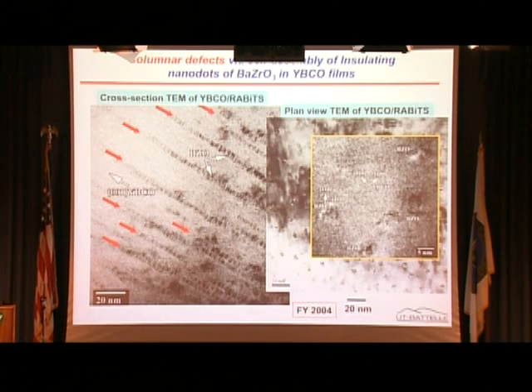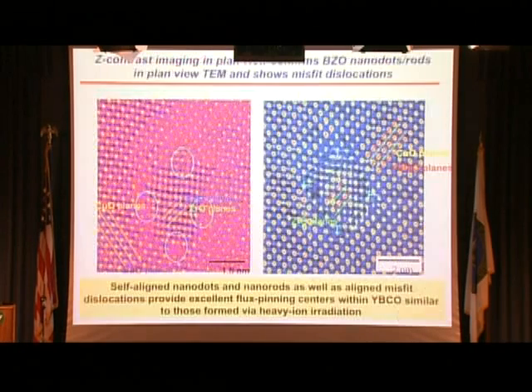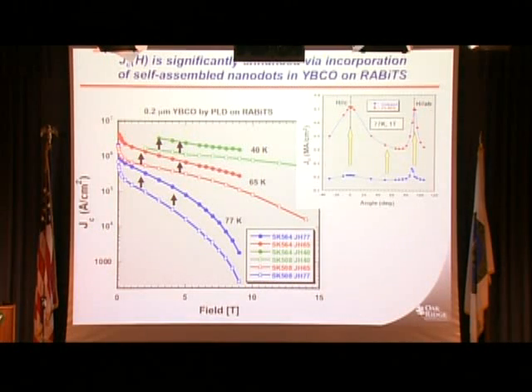You can go still higher in magnification into one of these dots and look at the atomic configuration, and you can see that they have these misfit dislocations, which in a column all align up. And so theoretically, this should be a very good way of pinning this vortex lattice that I mentioned to you about. And so indeed, when you put these columns inside a YBCO film on a substrate that I mentioned to you about,